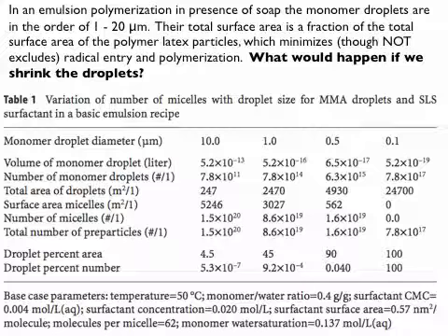Because I need my surfactant molecules to stabilize the very large surface area of my monomer droplets. So effectively, I've got no micelles and only monomer droplets, and now only monomer droplets play a role in the reaction. That's quite an interesting system, because if I have monomer droplets only and the water phase is no longer important, I can do reactions exclusively in really small droplets, and I would simplify my system a lot.